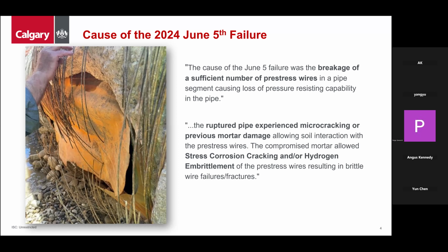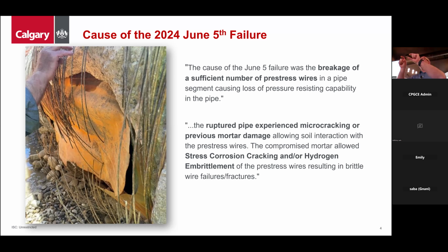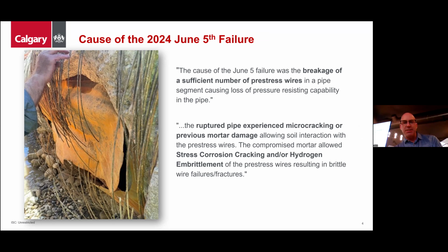In other words, for some of these pipes, the mortar is susceptible to sulfide attack and/or chloride attack. So the chloride attack on that outside mortar. Therefore, what we're seeing is that the chlorides from the outside soils had most likely penetrated through those micro cracks that we weren't able to see.